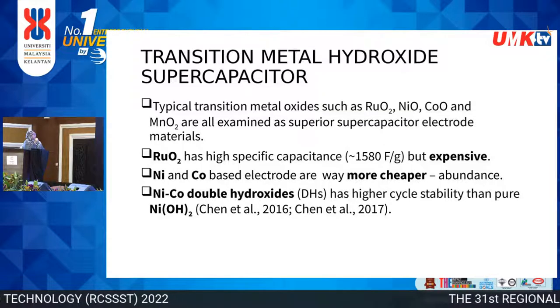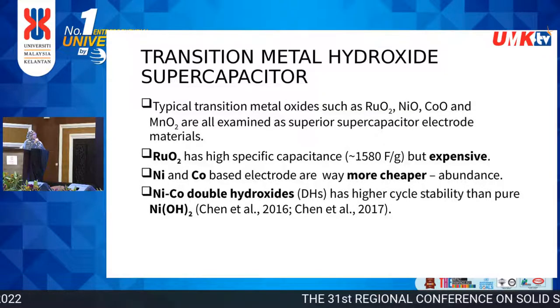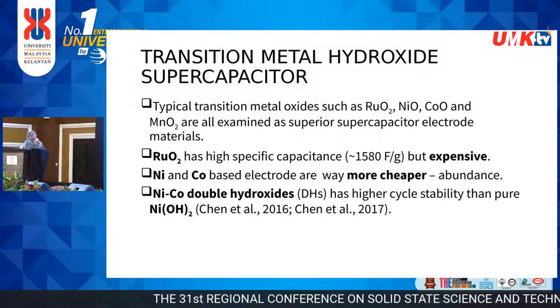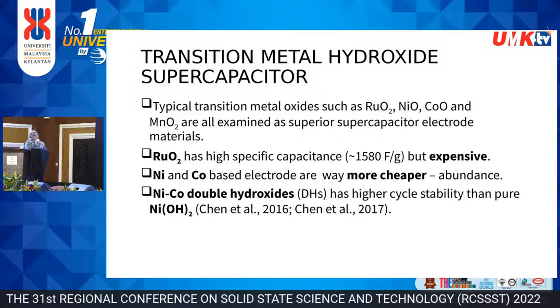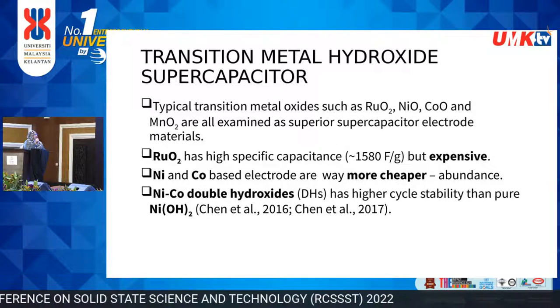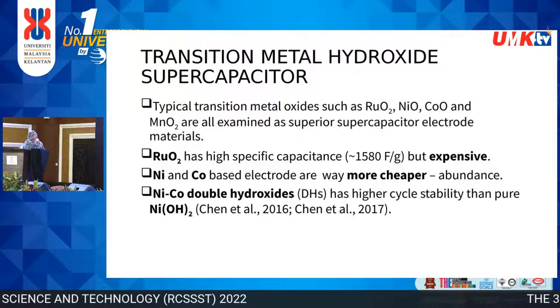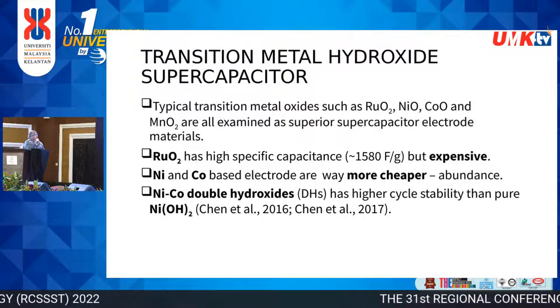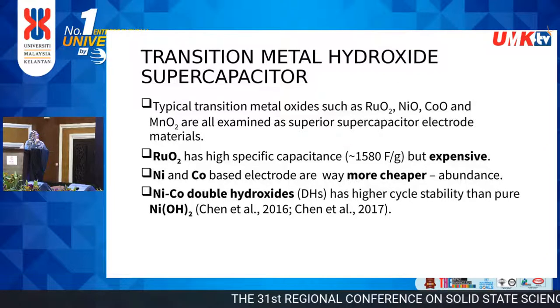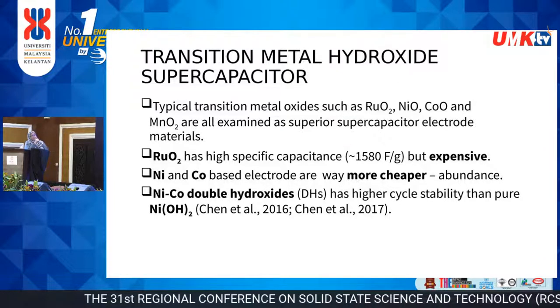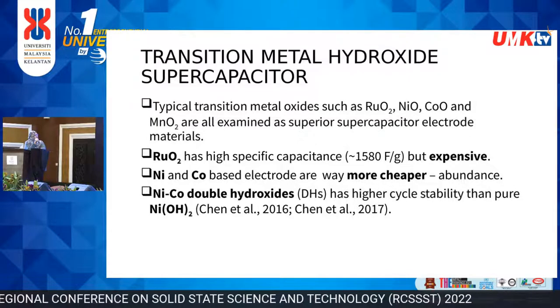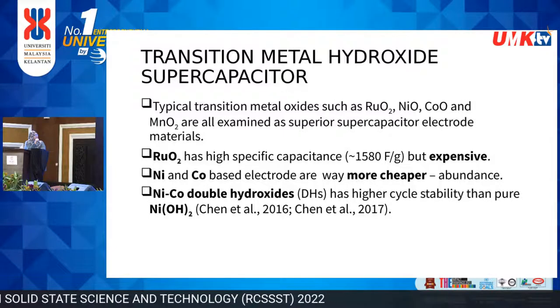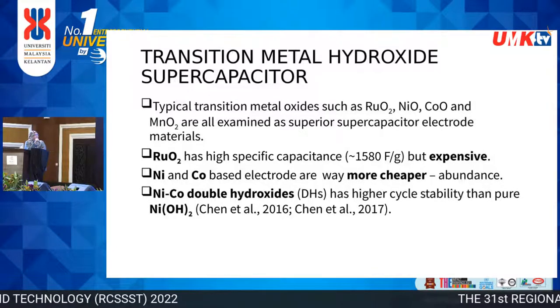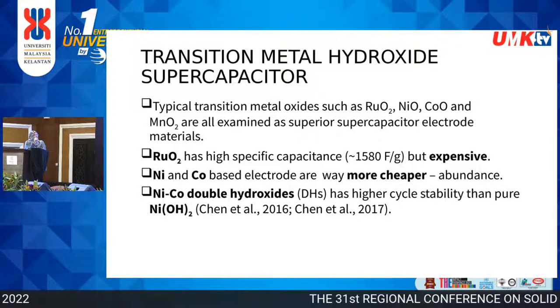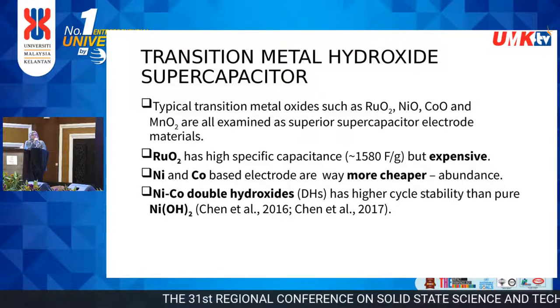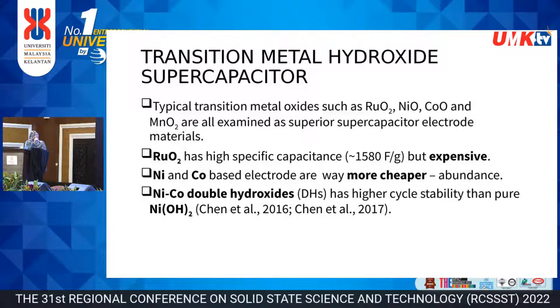Transition metal hydroxide supercapacitor. Typical transition metal oxides such as ruthenium oxide, nickel oxide, cobalt oxide, and manganese oxide are all examined as superior supercapacitor electrode materials. Ruthenium oxide has high specific capacitance, about 1,500 farad per gram, but ruthenium is very expensive. Nickel and cobalt based electrodes are way cheaper, plus abundant. Nickel cobalt double hydroxide has higher cycle stability than pure nickel hydroxide. So, in this work, we focus on developing nickel cobalt hydroxide electrode material for supercapacitor.